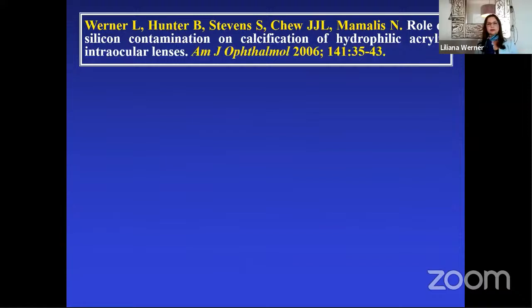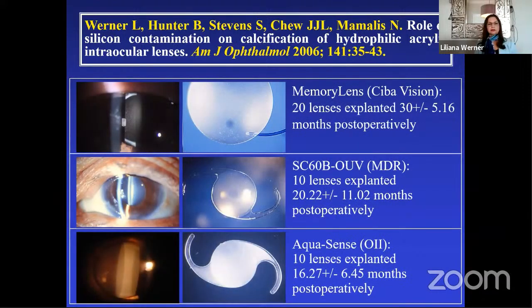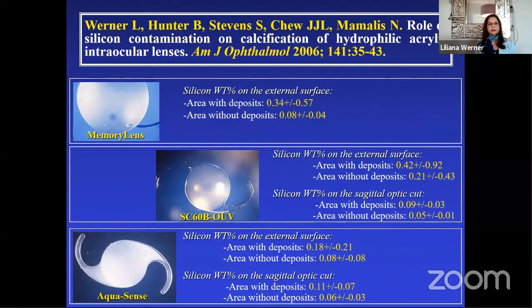This led us to initiate a study evaluating the possible role of silicon contamination on the process of calcification of other hydrophilic acrylic lenses, such as the Memory lens, the SC60B-OUV, and the Aquasense. In this study, we were able to demonstrate with surface analysis that the concentration of the element silicon was always higher in areas with calcified deposits with these three lenses.